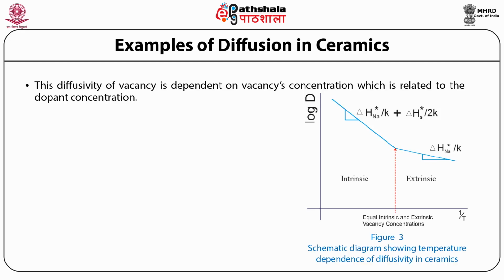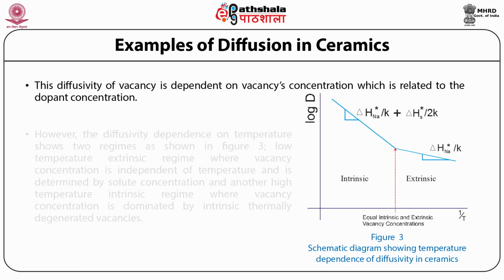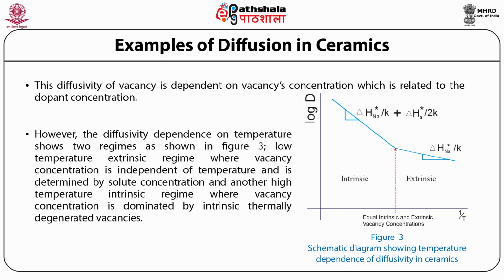However, the diffusivity dependence on temperature shows two regimes as shown in this figure. The low temperature extrinsic regime, where the vacancy concentration is independent of temperature and is determined by the solute concentration, and another, the high temperature intrinsic regime, where the vacancy concentration is dominated by the intrinsic thermally generated vacancies.